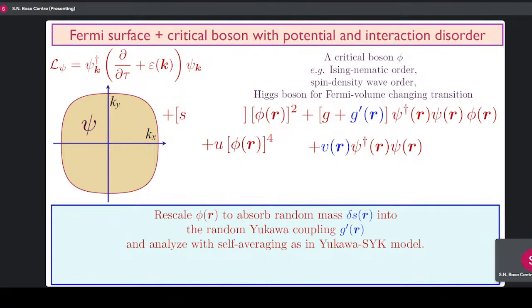So we keep, in addition to the random coupling, also the spatially uniform coupling. Basically what we have done is taken the random mass term and put it into this G prime by this rescaling trick. This is a trick which could be dangerous because there are some other terms we're generating. So we don't know if it's really going to work, but let's assume it works. And if I have 8 minutes, I will tell you about our recent work. We can now actually see when it works, and when it doesn't.